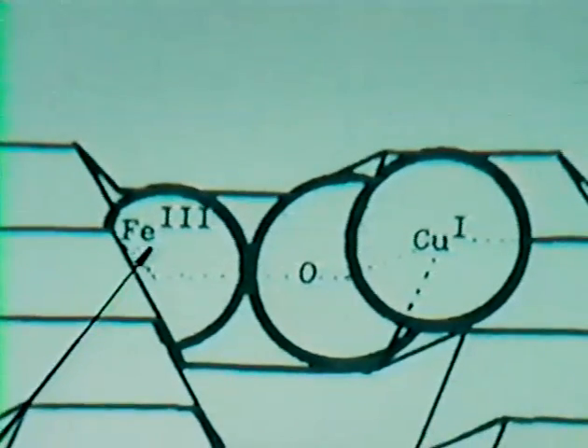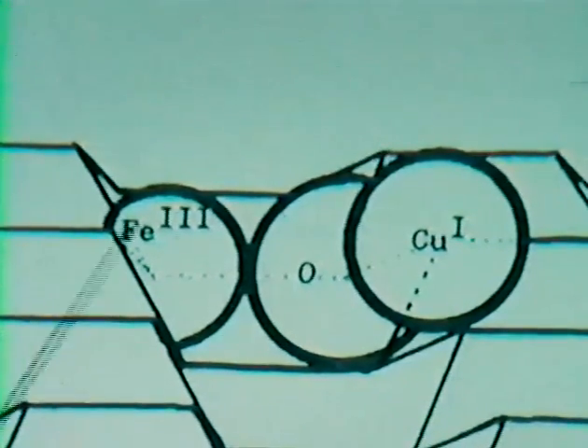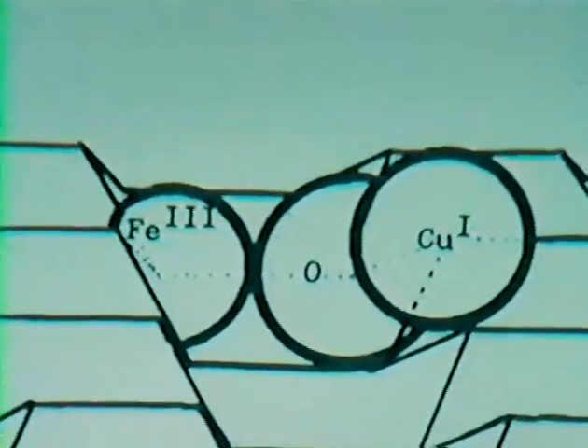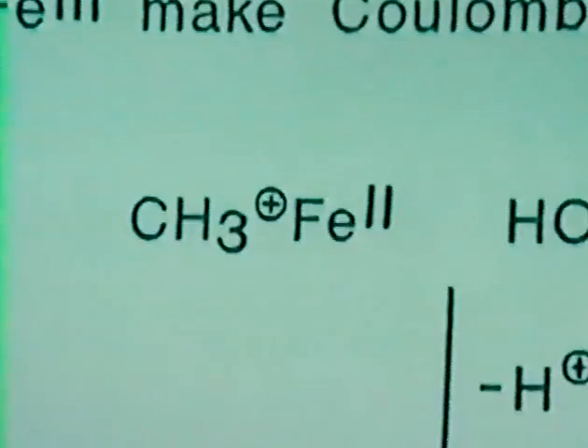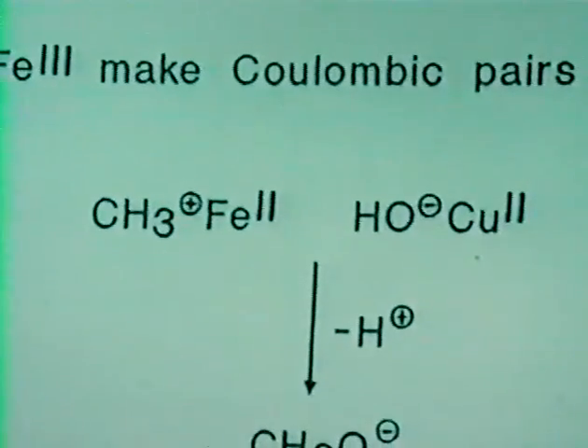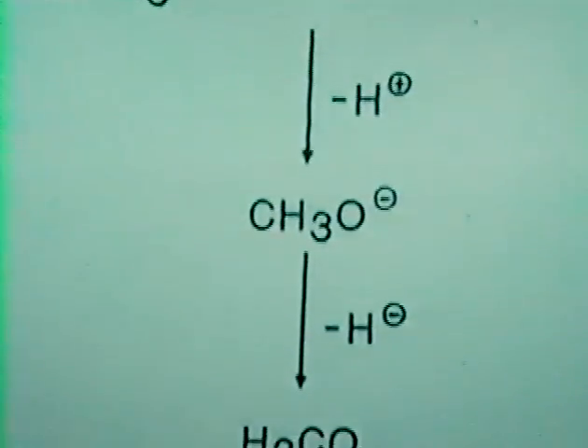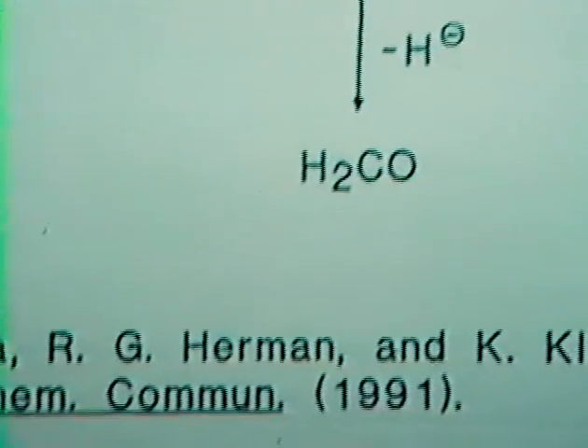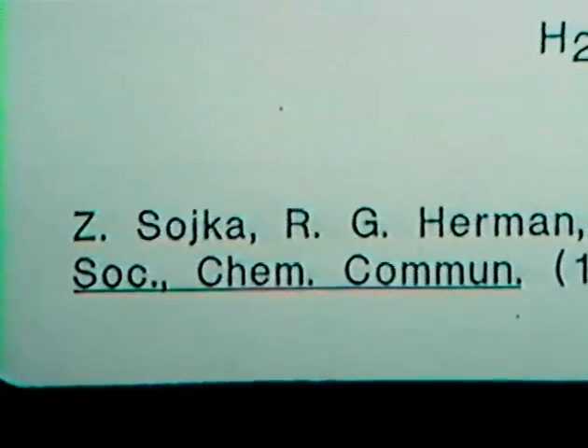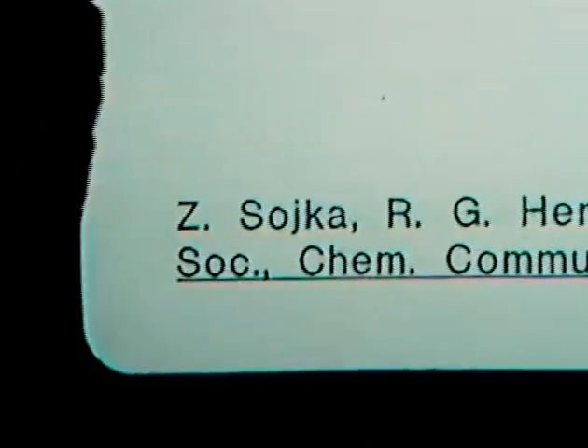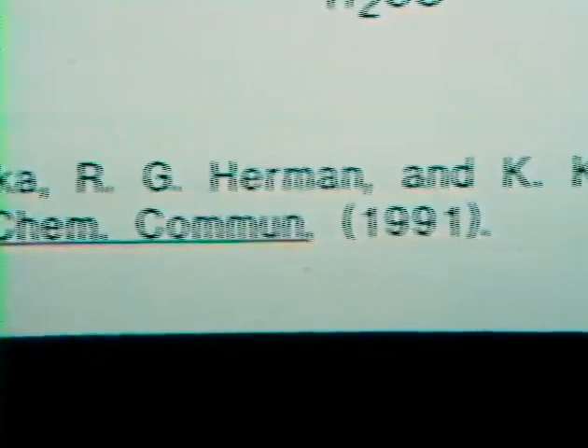What we did, we implemented the idea of a redox pair on copper and Lewis acid here, so that we would put a copper instead of one zinc, iron instead of the other zinc, have them bridged by the oxygen of the zinc oxide, and that way we would create these Coulombic pairs that also exist in the zeolites. There is actually a proof, experimental proof, that we created. These are low concentrations, 1% of copper and 1% of iron in zinc oxide. And the proof comes from high resolution ESCA. I won't go into the detail, although I can share it with you.